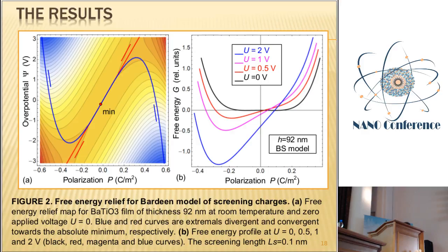Well, and the results are so that for the first model, which is a model of linear screening, the free energy relief is the usual double well potential, typical for Landau's theory. When you apply external voltage, one well of the potential becomes deeper, and another well of this potential disappears. Classical phase transitions, either for a ferroelectric or for a ferromagnetic in an applied external field.